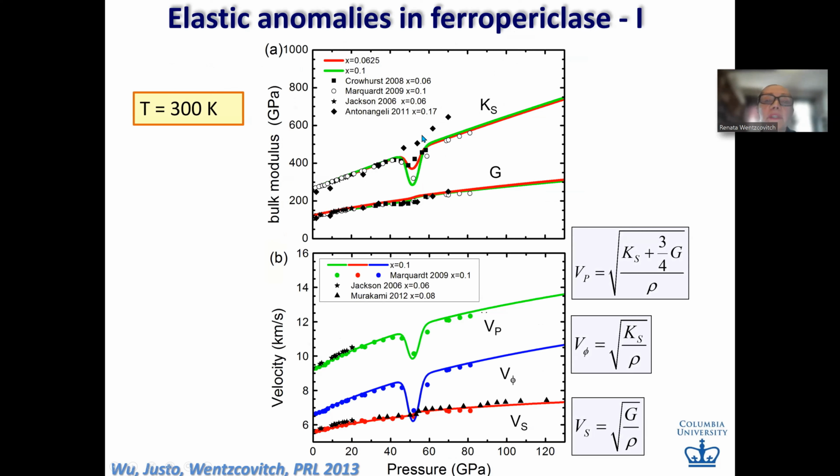And these are the three experiments that were so different, but it's the Brillouin scattering that said C44 is 0. That is the one that makes more sense. So there is agreement between experiments and calculation, with Brillouin scattering more than anything else. And this is the compressional velocity and the shear velocity for several experiments with different compositions. And this is ours at 10%. The solid lines are our results at 10% iron.